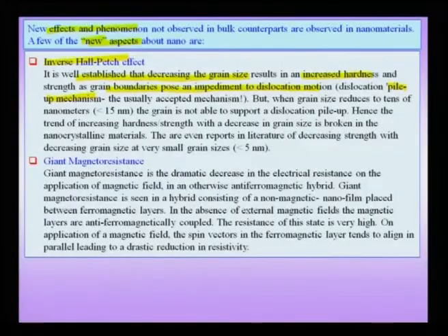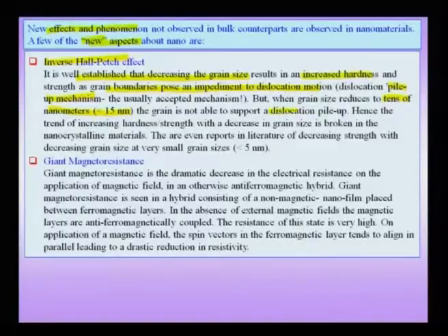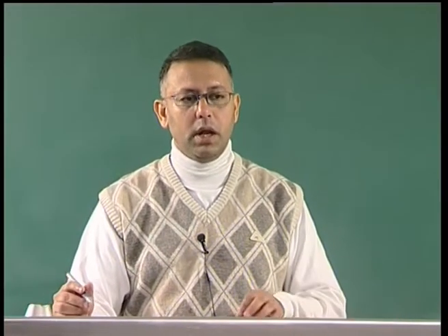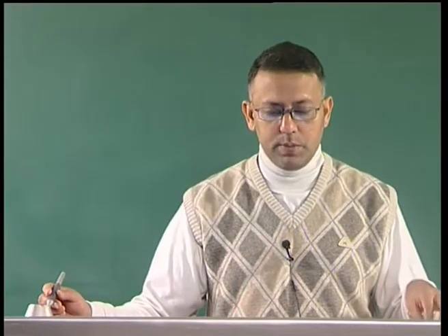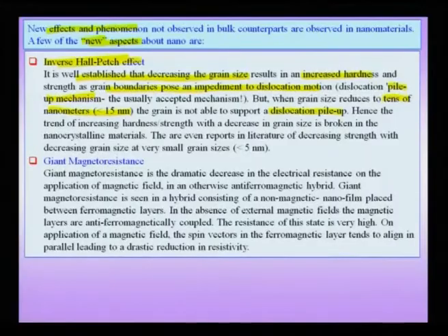But this Hall-Petch relationship, on one hand, in very large grain size materials has been questioned, but that is not our region of interest. In very small grain sizes, when you are talking about tens of nanometers, typically less than about 15 nanometers, it has been observed that the grain itself cannot support a dislocation pileup. And it is seen that the Hall-Petch relationship actually breaks down. In very specific experiments, of course, many of these experiments still need confirmation in a larger spectrum of materials, but there have been reports that not only does this traditional Hall-Petch behavior break down, but there can actually be something known as the inverse Hall-Petch relationship.